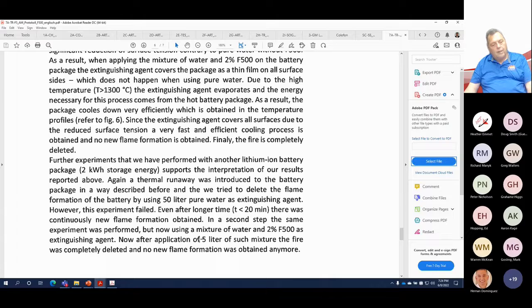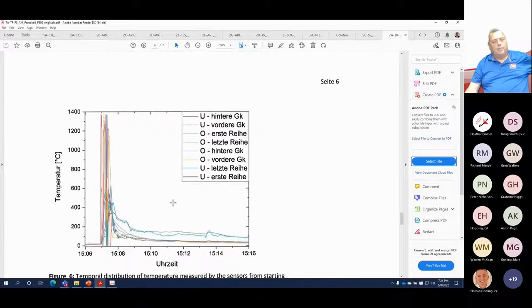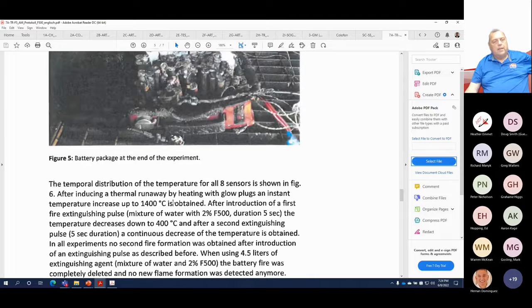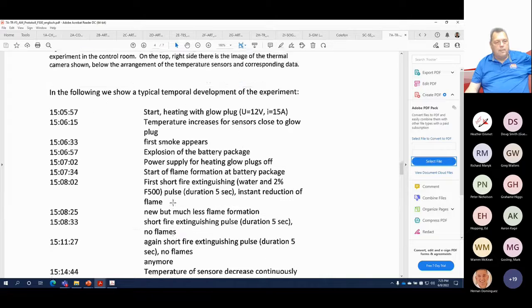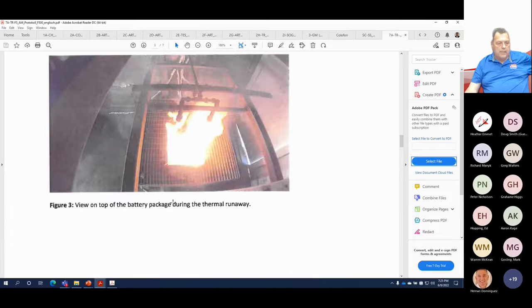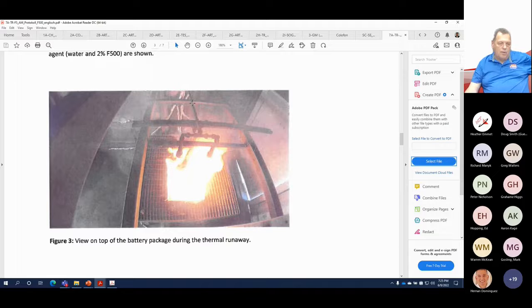They had the same results 2 times in a row with the F500, but we couldn't extinguish it with the 50 liters of water. So I would like to say we're 10 to 1 more effective than water. The problem is the 50 liters of water did not extinguish the fire. So these 2 nozzles here go back to a 50-liter pressurized tank, and that's how they dispensed both the water and the agent. So on one hand, the 50 liters of water didn't put the fire out, didn't reduce the temperature, and on the other hand, 4.5 and 5 liters of encapsulator agent did. We have a remarkable technology here.